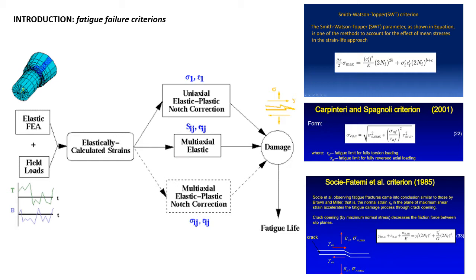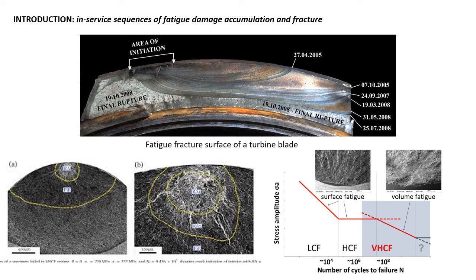Most of such criteria are formulated for a given loading condition only, I mean for low or high cycle fatigue. Some of the criteria are developed so that they can take into account the loading history, but they are mainly not aimed to switch between different loading regimes automatically. The study on the in-service fatigue failure of different engineering elements shows that fatigue crack often initiated under one loading condition or regime and then turns to the propagation under another one.